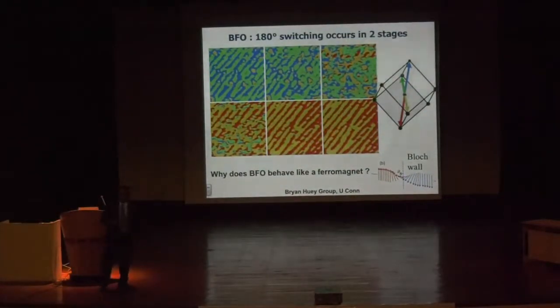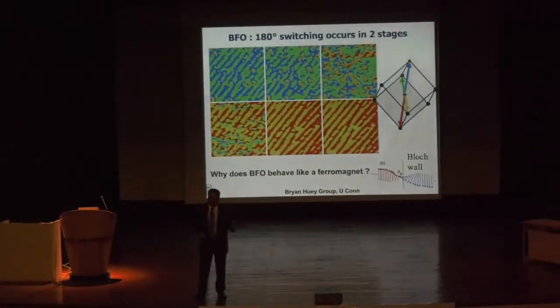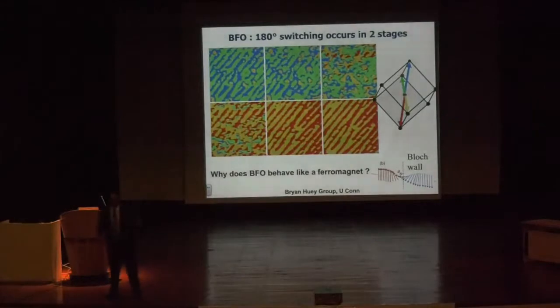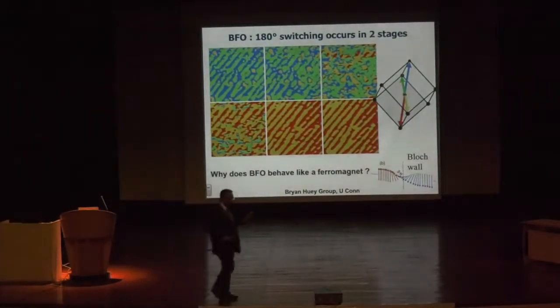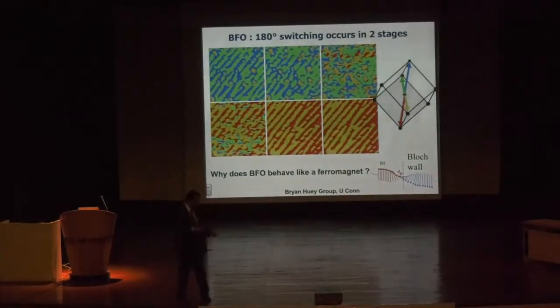But what was fascinating was that for each of the domains, that rotation process happened in 2 steps. And at that point, nobody had really described the switching of a ferroelectric in a 2-step process. So in this particular case, the ferroelectric was behaving more like a ferromagnet. In a ferromagnet, you're dominated by exchange interaction, and therefore you're simply rotating the polarization, also the magnetization, through a Bloch wall or a Néel wall, but the magnitude of the moment does not dramatically change.